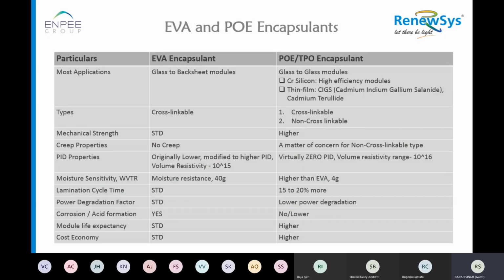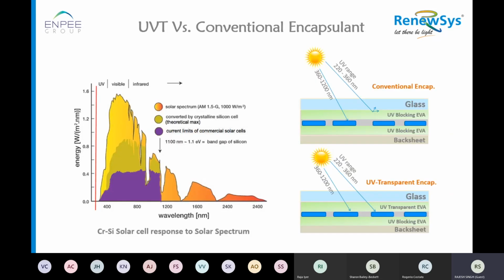Now among various encapsulants, we said EVA and POE are the two dominating ones. And within EVA and POE, there are two variants of encapsulant. One is UVT and the second is conventional. UVT is nothing but ultraviolet transparent, which is a new entrant into the technology of PV, which came around 3 years back. If I give a very brief comparison, in conventional encapsulant there is some formulation in the recipe which makes light get blocked if it is less than 360 nanometer. The purpose is to block these UV rays, which were supposed to be harmful for the cell and the backsheet below it earlier.